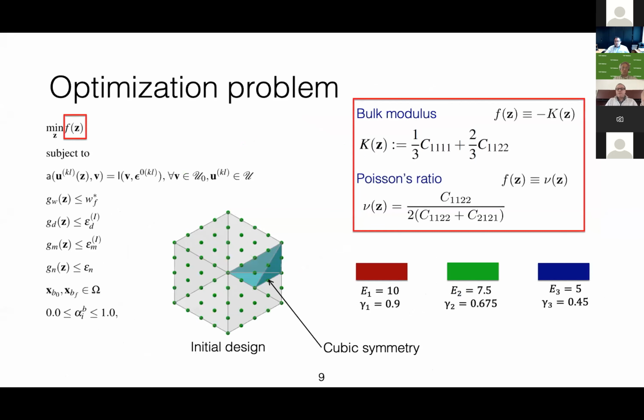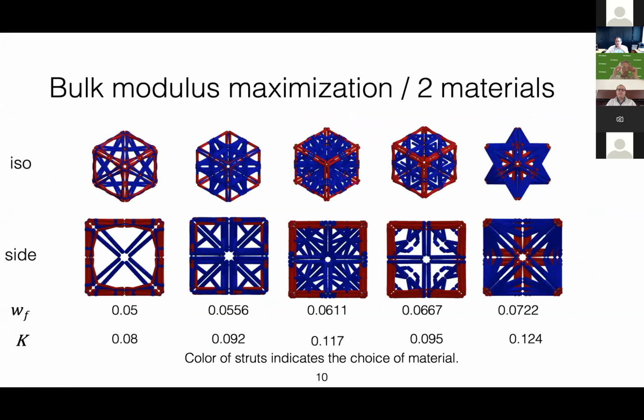So I'm going to give 2 examples of problems that we solved with this formulation. One is to maximize the effective bulk modulus of the lattice. The other one is to minimize the Poisson's ratio. We're going to employ these 3 materials, which are made up materials with different moduli and physical densities, and we enforce cubic symmetry. One interesting feature about our formulation is that we impose a weight constraint, and we like that because with a weight fraction constraint, the optimizer chooses the right proportion of the different materials as opposed to imposing arbitrary volume fraction constraints on each one of the materials.